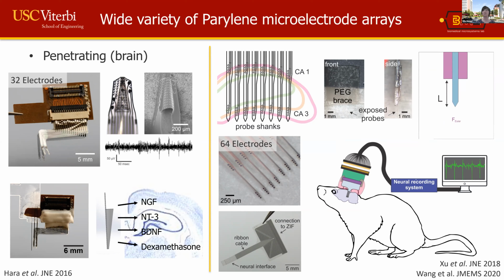external recording systems. If you have one of these very long floppy devices, it turns out it's difficult to implant that into the brain. You have to support these soft polymers. Otherwise, they undergo mechanical buckling and essentially don't insert into the brain when they're not stiff enough to actually penetrate. And so the mechanical trick that we play is we temporarily shorten the length of the probes, as shown in this middle set of figures here, by embedding the back end in a biodissolvable material called polyethylene glycol. And so what we can do then is leave the exposed length quite short, and this becomes much stiffer in this format, and we're able to insert the probes bare into the brain. So we don't increase the cross-section to insert them into the brain.